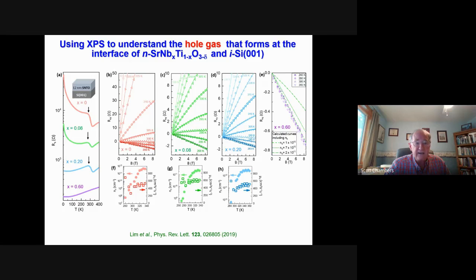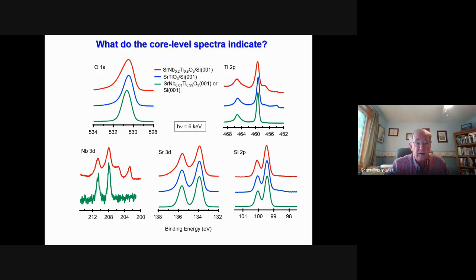Well, we decided to try to probe this. Because it happens with thicker films and not with thinner films, like 12 nanometers in this case, conventional XPS is useless because we can't see the interface. So what we did is we took the samples to Diamond Light Source and we measured hard X-ray XPS on these samples. And so here's what we learned. We did the experiments with an X-ray energy of 6,000 eV.